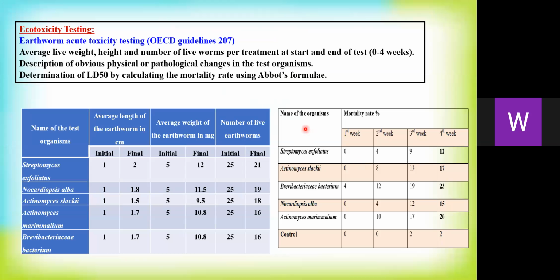Acute toxicity test: the average live weight, length of the earthworm, weight of the earthworm, number of earthworms, and mortality rate percentage. Initially, 1 centimeter length was observed in the earthworm. After the 1 month study, the length of the earthworm ranges from 1.5 to 2. Similarly, 5 mg of earthworms was taken for the study, and after 1 month you can see an increase in the weight to 9.5 to 12. Initially, 25 earthworms were maintained in the setup. It has been slightly reduced to 21, 19, 18 and so on.